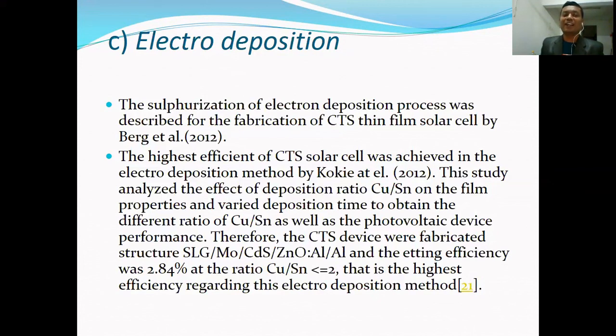This study analyzed the effect of the deposition ratio of copper to tin on the film properties, varying the deposition time to obtain different copper to tin ratios, as well as the photovoltaic device performance. Therefore, the CTS device was fabricated